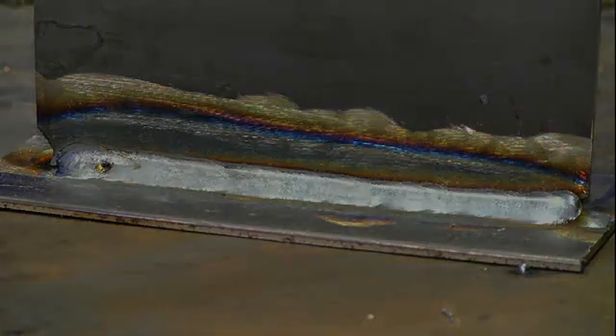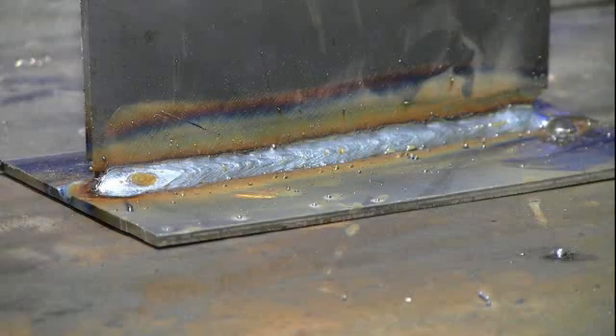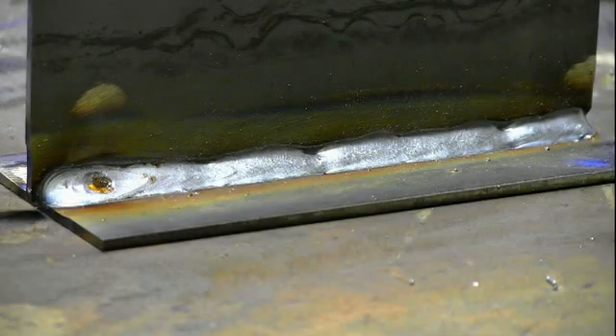So now that we've seen what a good set of parameters looks like, and what a set of parameters looks like with too low a voltage and then too high of a voltage, I'm going to take the 27.5 volts and the 600 inches per minute parameters, and I'm going to drop the wire feed speed now to 450 inches per minute. So here we go.